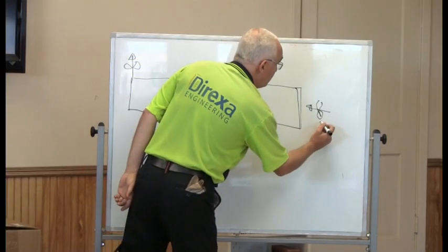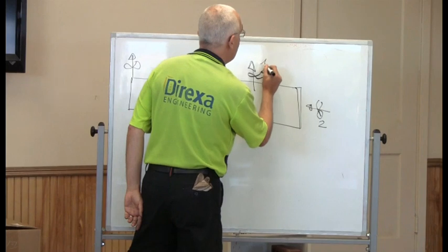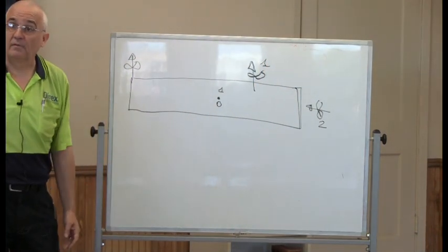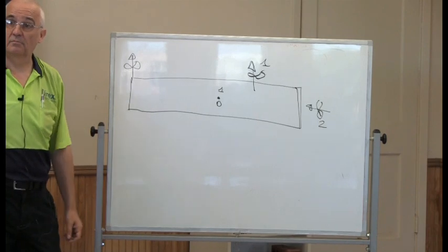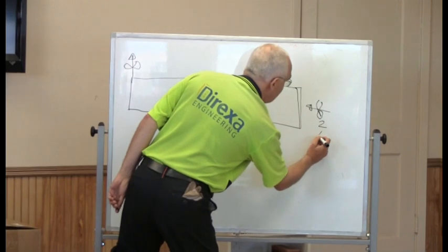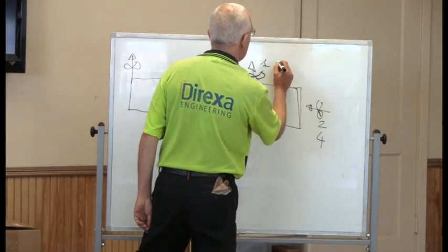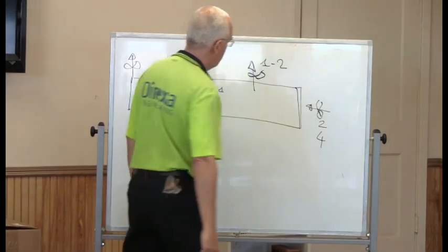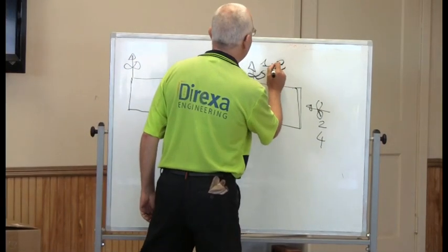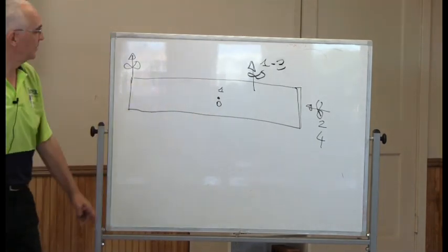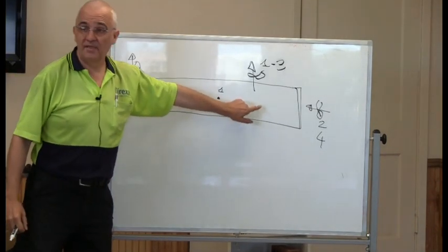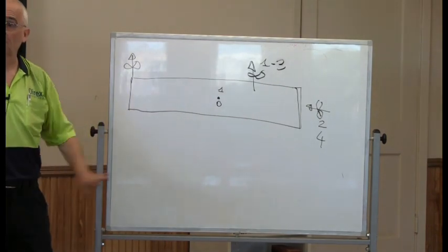If I put 2 and remove 1, we have 1 pound, we have zero pressure, we're good. Let's say now I put 4, but I remove 2, 3, sorry. My bad, I still have 1. Do I have the same cooling capacity here? No.